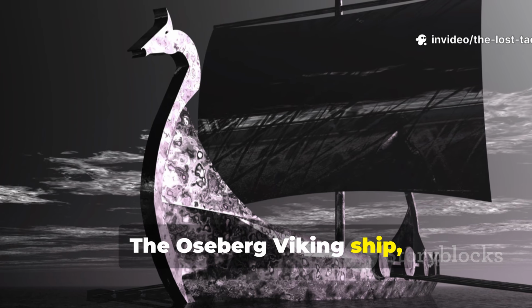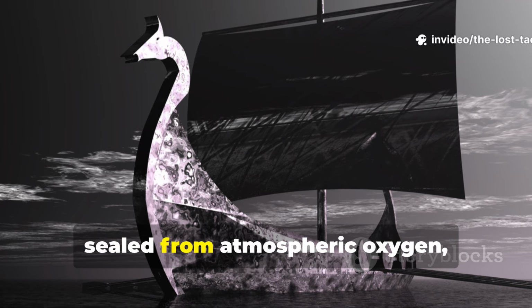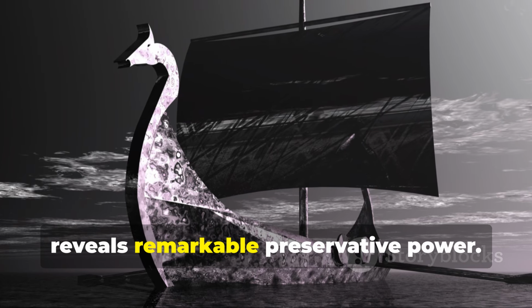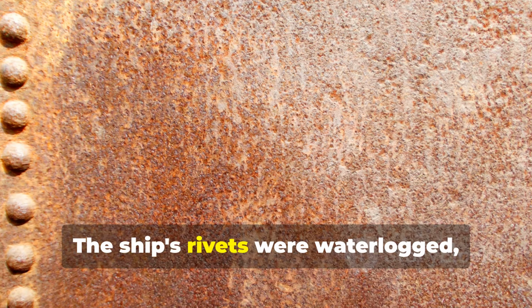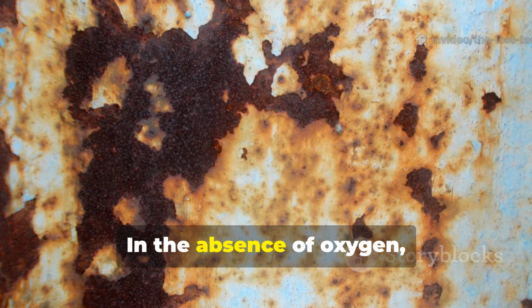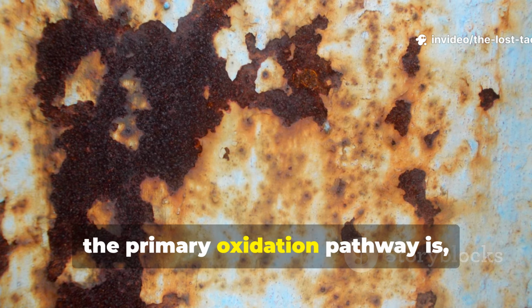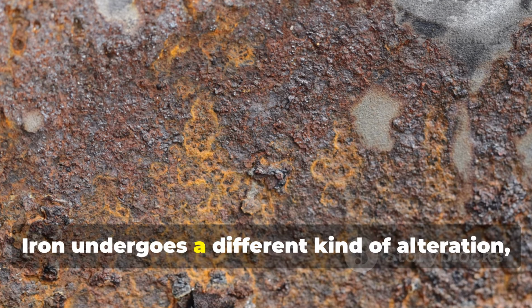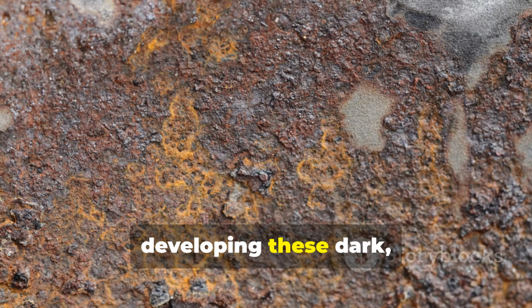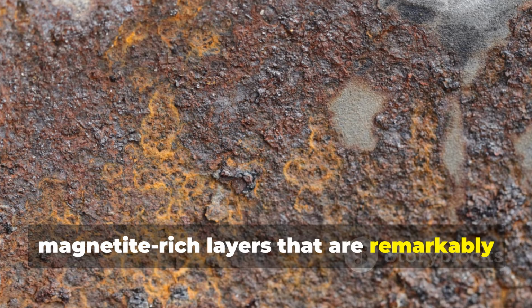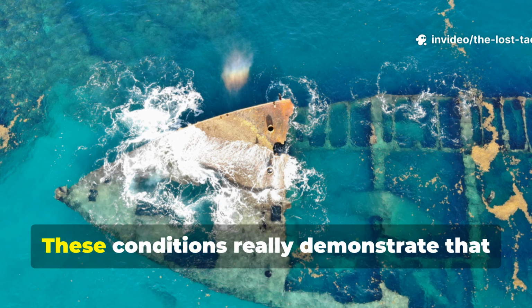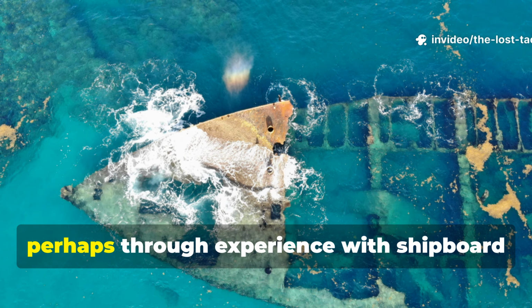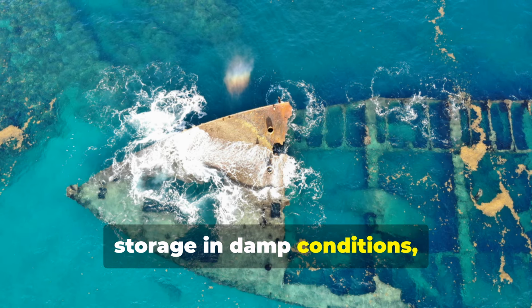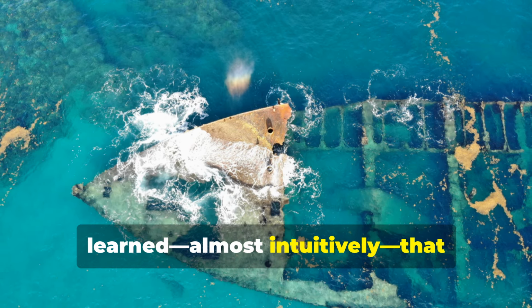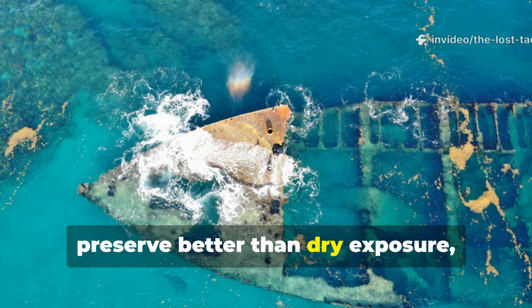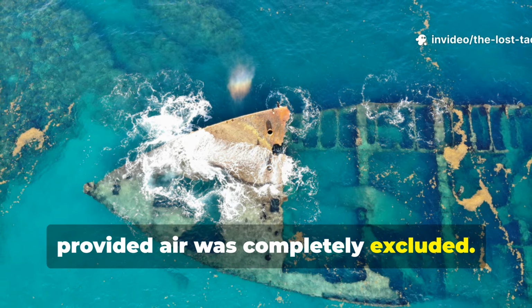The Oseberg Viking ship, which was buried in a Norwegian mound sealed from atmospheric oxygen, reveals remarkable preservative power. The ship's rivets were waterlogged yet oxygen-free. In the absence of oxygen, the primary oxidation pathway is blocked. Iron undergoes a different kind of alteration, developing these dark, magnetite-rich layers that are remarkably stable over centuries. These conditions really demonstrate that the ancients, perhaps through experience with shipboard storage in damp conditions, learned, almost intuitively, that saturation with water could actually preserve better than dry exposure, provided air was completely excluded.